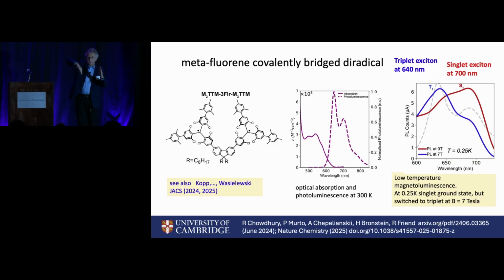And the photoexcited state is that charge transfer state, that Mott-Hubbard excitation, where we've moved an electron from one side to the other, and the energy of that is the charging energy. It's not an electronic gap, it's the Coulomb charging energy, about 1.8 eV. That is the 700 nanometer emission. It comes out efficiently, but more slowly.